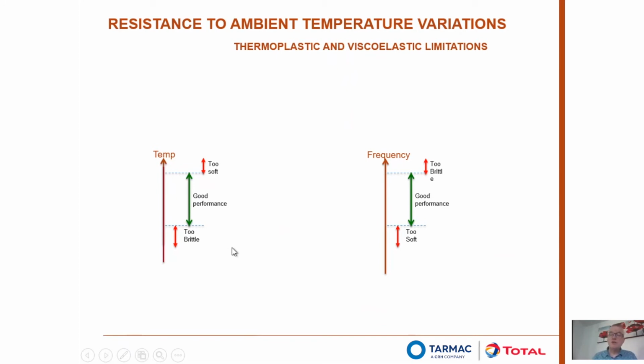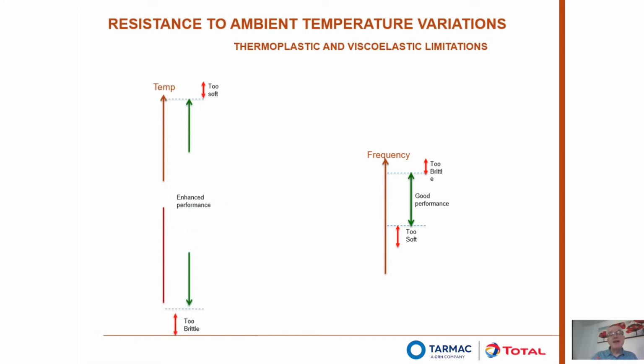Conversely, in winter, where we're having extreme cold weather, we could be in this area where the bitumen becomes too brittle to be of much engineering use. So what we're trying to do with polymeric intervention is stretch those areas so we get an enhanced performance in the middle, so a better performance than just penetration grade bitumen, but we're widening that temperature range significantly.